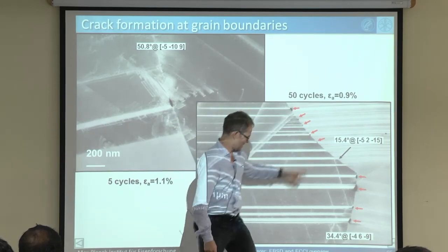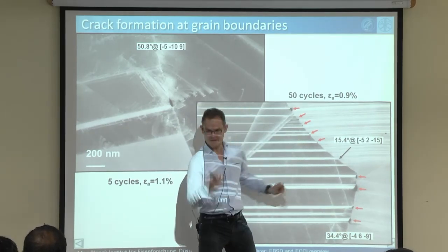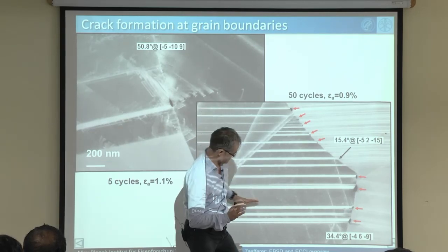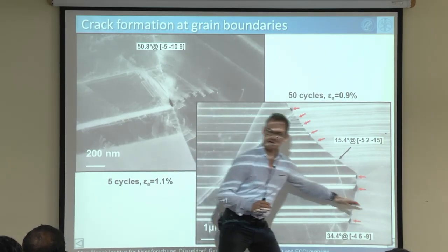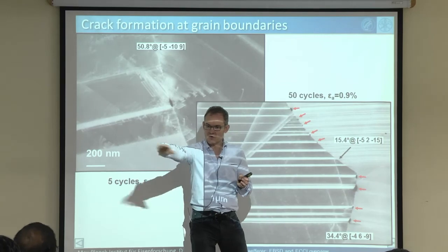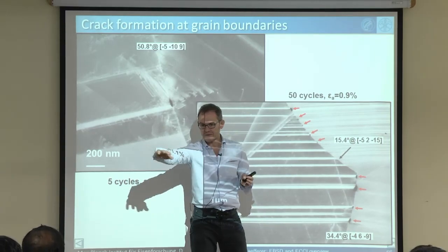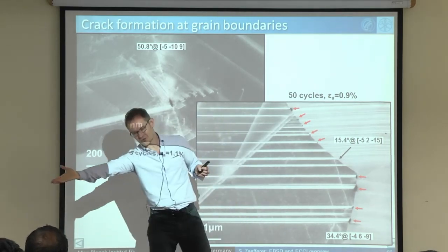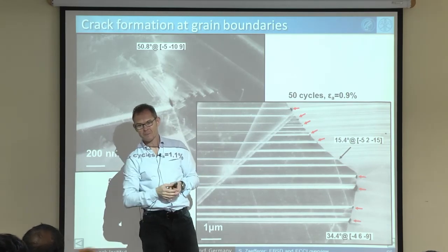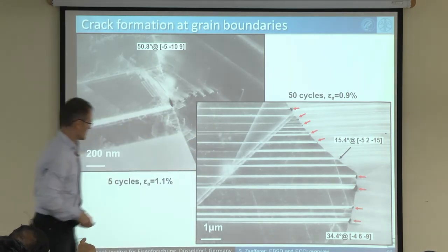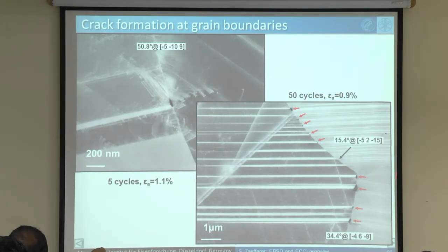It's a large angle grain boundary, and here it's even 34 degrees, and still the structure looks for alignment of 111 planes, because once you create an epsilon martensite on a 111 plane, in the neighboring grain you want to continue with this deformation. So this cracking at the boundary ahead of the epsilon martensite, you are saying it is because of the hydrogen? Yes, when you have no hydrogen, there's no cracking. Now, of course, there's also much less epsilon martensite.